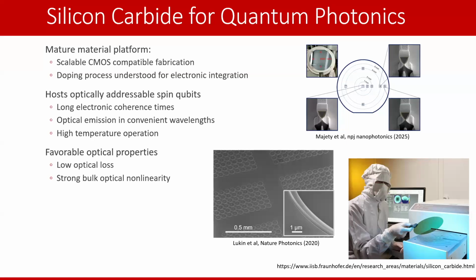And of course, it hosts optically addressable spin qubits with long electronic coherence times. It's got optical emission in convenient wavelengths, and by convenient wavelengths, I mean those where we can take optical fibers and connect them to other things with relatively low loss, so we can extract photons from this platform relatively easily. It also has high temperature operation, aka you can do this in a closed cycle cryostat at 4K. In fact, the defect that I've been working on primarily in my PhD, the silicon vacancy center, can actually operate up to 10K and above. And this makes building devices much easier than having to use a dilution refrigerator.